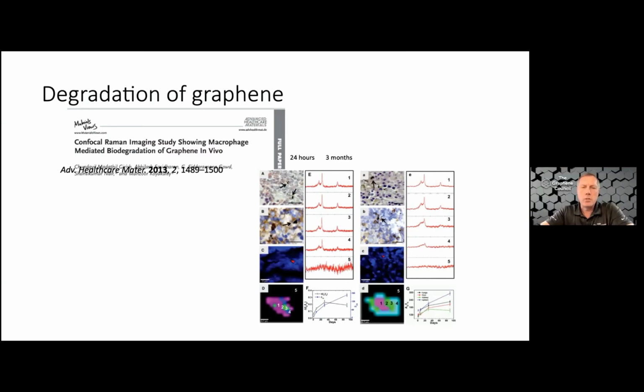Let's try to get just two more questions in here. Another of our audience is asking, why not just incorporate the graphene directly into a polymer and make a composite, as opposed to a CVD process where it's a monolayer that is added and adhered to it? What would be the reasoning? Extremely good question. In our case, we would like to have a conducting layer on the macro scale. I measure the graphene side to side, centimeters away sometimes. So you cannot do that with a polymer.